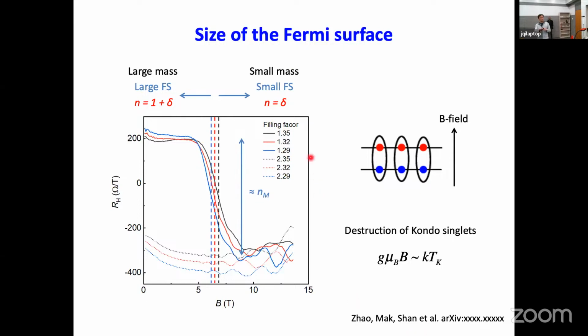So before the breakdown, the magnetization grows slowly, and then it has a sharp growth. So there is a differential susceptibility peak at that transition here, and then it saturates, because you break down the Kondo singlets, but the local moments still saturate, right? Because remember that the exchange energy scale between the local moments in this type of system is small. It's not like in the real system where they have strong exchange. You don't really saturate there, but here we saturate already. Yeah.